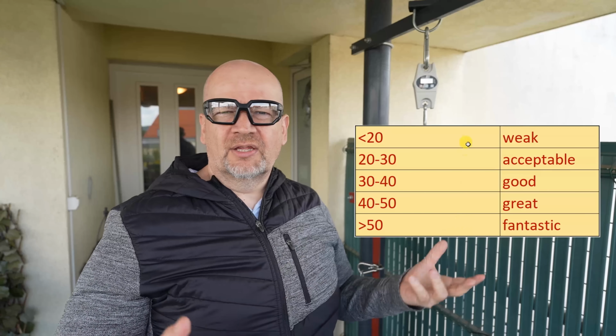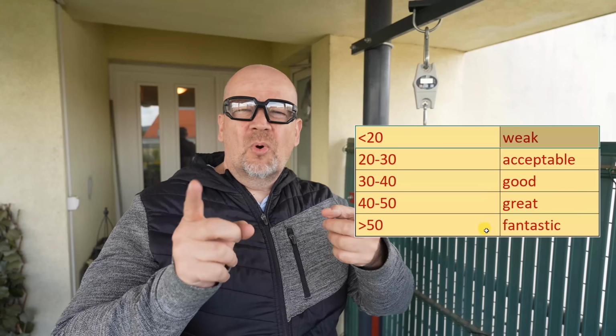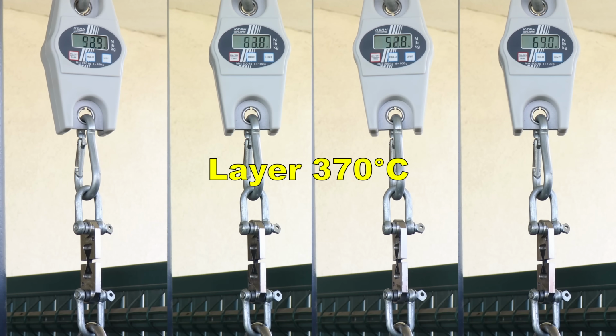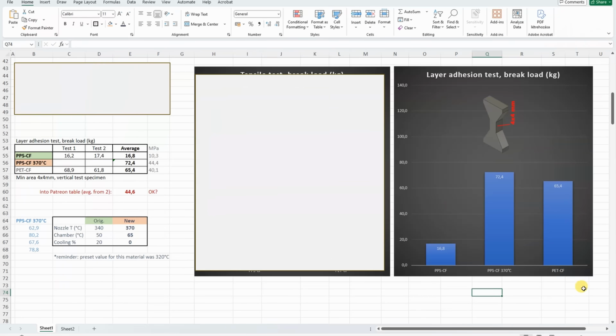This is my rating for the layer adhesion with these test objects, and we can see that this is weak. What do you think? What will be the new break load with these improved settings? This also means that PPS layer adhesion is very sensitive to settings, even more compared to ABS. Definitely should pay attention to this. Even PET-CF has great layer adhesion, but let's concentrate on these two materials. This is what we will get with the default settings. Well, actually even less, because as a reminder, I raised the temperatures from 320 to 340 degrees, because this is the default setting for this material in the slicer. And if we change the settings from this to this, look at this huge difference in the layer adhesion.